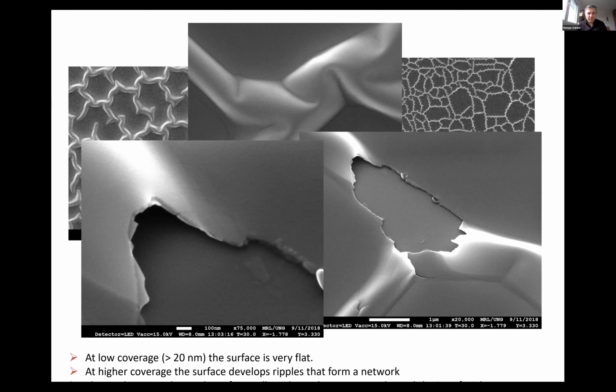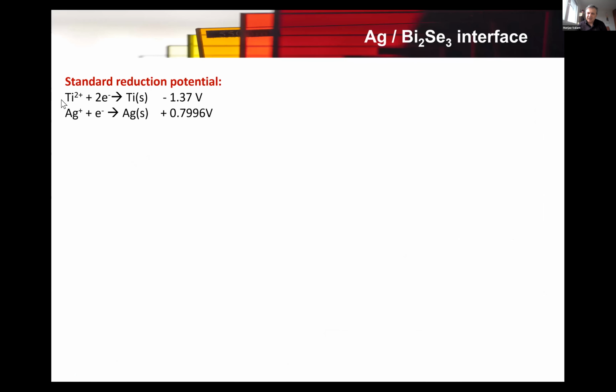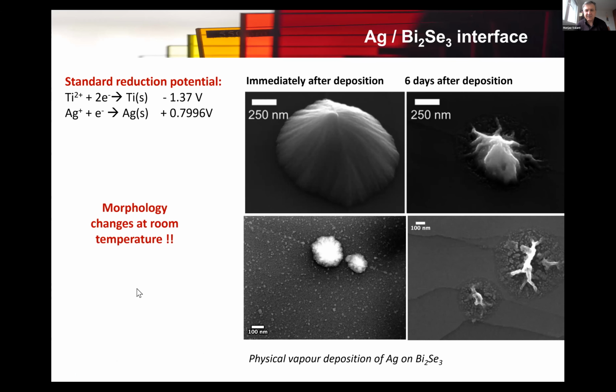Okay, now we are moving on. We said, okay, titanium is reacting. Let's take something more novel. Let's see what silver would do. So we deposited some silver on the top of bismuth selenide. We left it there on the shelf for a week, and then we looked at this deposition again. What we have seen is that with time, in 6 days, these shapes significantly change. They shrank, and also these small spots just disappear, as you see. So obviously something is happening also with silver, and we want to see what that is.